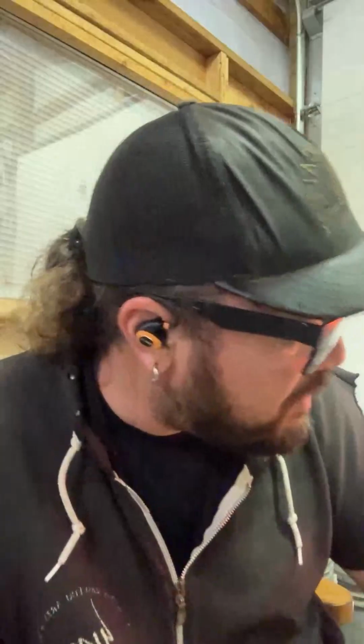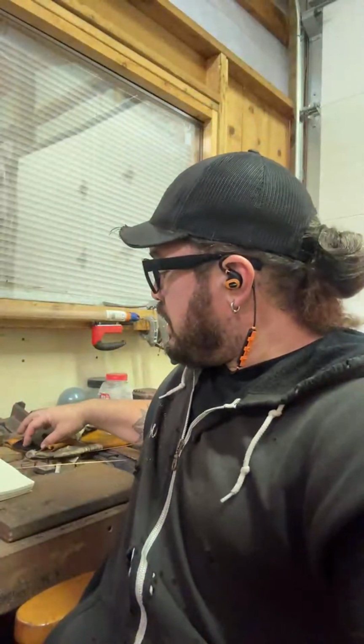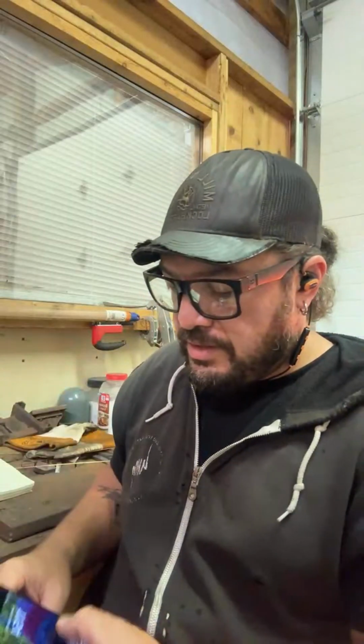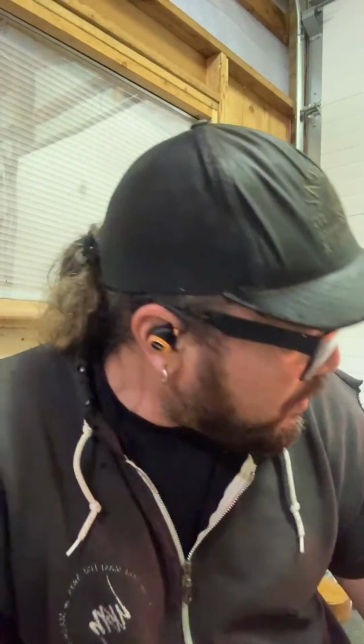That's weird to say 4-to-1 in relationship to a 6 inch by 1.5 inch piece of material. Anyways, okay, I'm going to pull this out and get squishing on it again. And then after this, all we're doing is keeping it hot and working it. We're going to draw this billet out. And at a certain point, I'm going to knock it out of square. But I won't do that probably before truing up the outside edges of the billet, and then I'll knock it out of square.